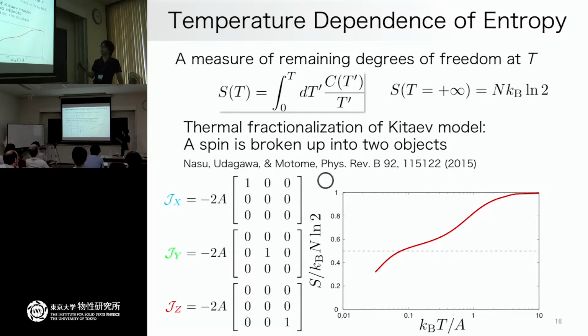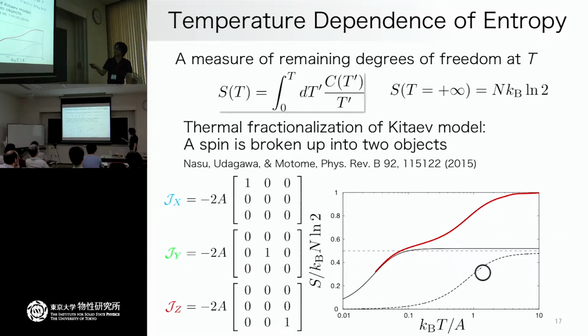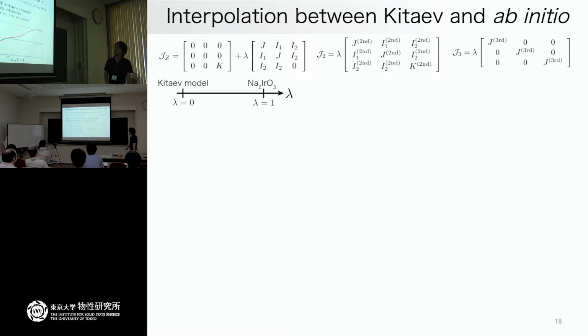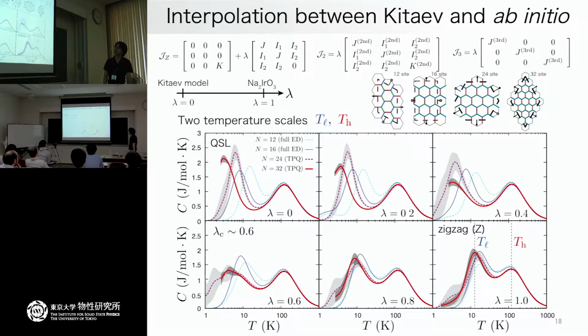So if you calculate the temperature dependence of the entropy, then we have this kind of behavior. And here we have some shoulder. And if you divide this curve into two smooth functions, then we can figure out that this shoulder is coming from the separation, or plateau, in the entropy. So this is nothing but a half plateau in the entropy. This signals the decoupling, or sorry, the division of the spin degrees of freedom into two objects, or two degrees of freedom. And this kind of separation is also found in the ab initio Hamiltonians.